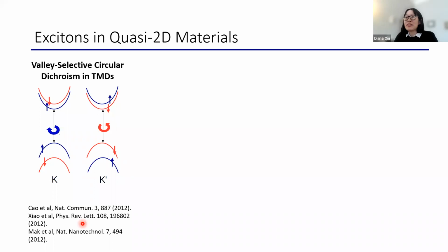So yes. In order to distinguish them, as you were hinting at, you can't really distinguish them within optical absorption because you're exciting both of the degenerate valleys. But you can distinguish them in the photoemission. If you shine light of one circular polarization, the photoemission maintains much of the same circular polarization. The other way is through some sort of spin transport, like a quantum spin Hall effect, which in this case, because you have different spins in different valleys, becomes a valley spin Hall effect.